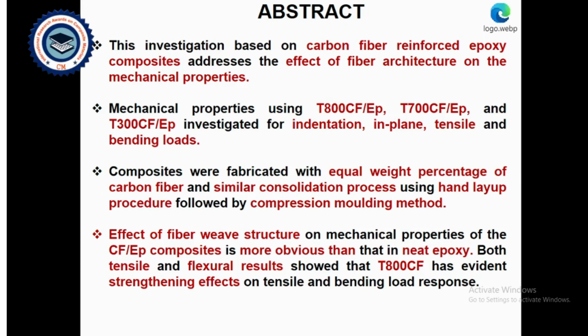Mechanical properties of T800 carbon fiber epoxy, T700 carbon fiber epoxy, and T300 carbon fiber epoxy composites were investigated for indentation, in-plane tensile, and bending loads. The composites were fabricated with equal weight percentage of carbon fiber, using a similar consolidation process: hand lay-up followed by compression molding. The effect of fiber weave architecture on the mechanical properties of the carbon fiber epoxy composites is more obvious than in neat epoxy.